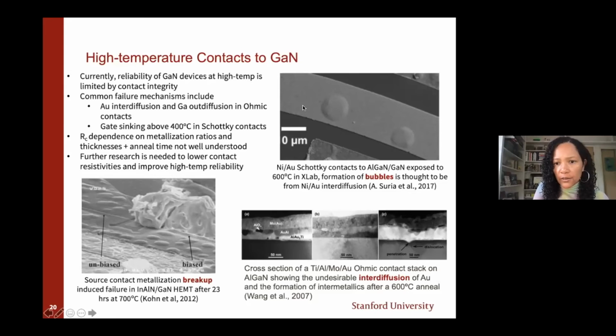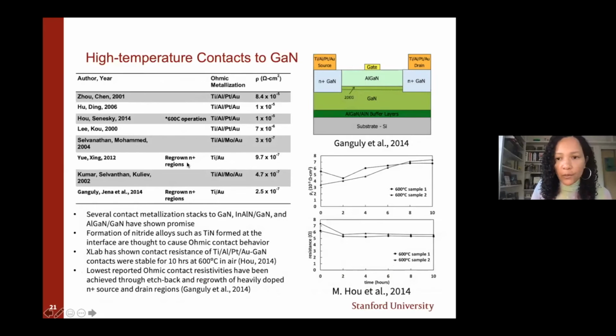So looking at the literature, there's all kinds of things that can go wrong. This is things that we've observed over the years as we've developed our fab process. So, in the early days, we started with nickel gold, our common Schottky contacts again, and we saw these bubbles that were forming, and we attribute it to nickel gold interdiffusion. Other groups have shown balling up of metal contacts and also interdiffusion of ohmic contacts into the gallium nitride. So it's important to know the evolution of these contacts in the same environment and also the same duration of the expected mission. So these are some of the work that we've done and also other folks as well.